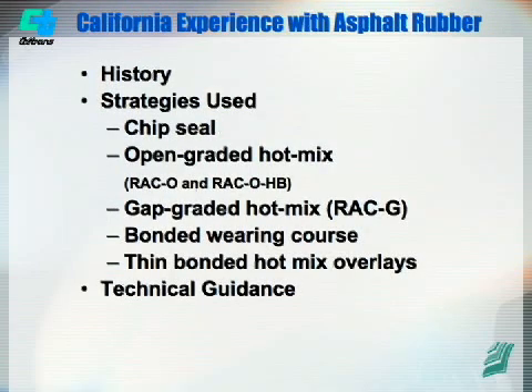Our history goes back many years, since the early 70s with chip seals. Then we developed experience with density graded and open graded hot mixes, where we use rubberized asphalt concrete open graded and rubberized asphalt concrete open graded with high binder. The binder content in the regular asphalt rubber open graded is about 20% more than the conventional open graded, whereas with the high binder it's about 65% more than the conventional open graded with just conventional asphalt.